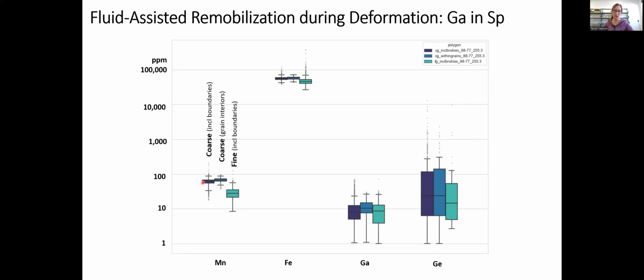And I've included those polygons we just saw, where it's coarse-grained areas but includes a few grain boundaries. That's the darkest one. And then I also did other polygons where I just included the core of the grains, so excluding grain boundaries, just to see how much of a difference that makes in the composition. And you can see that in general, coarse-grained sphalerite has higher manganese. So we're losing manganese when we recrystallize it.